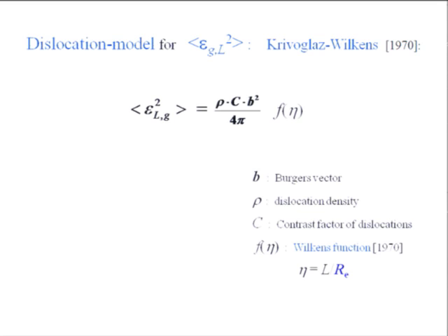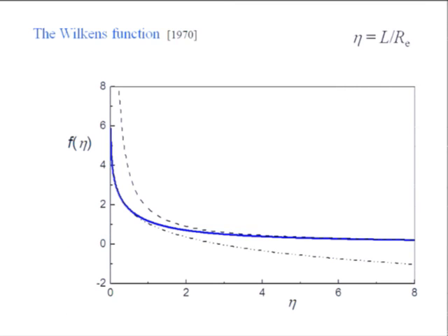It tells you how far the strain fields of a dislocation can reach, because if you have a dislocation ensemble, you can think of a dislocation gas, the many dislocations screen each other. The strain field will not go infinitely far, but it will concentrate around a certain region, and this we call the effective outer cutoff radius.